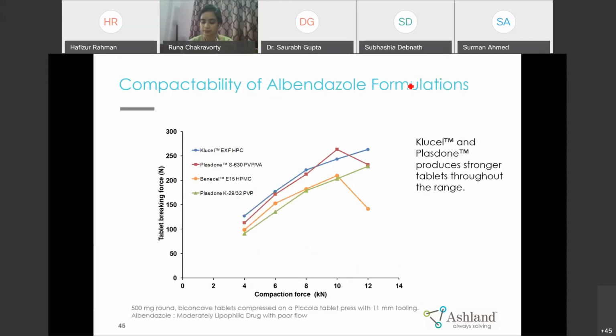Coming to albendazole, which is less hydrophilic or less soluble than metformin. Here you can see that we got the stronger tablet with Klucel, and next to Klucel with copovidone, but there is capping at 10 kilonewton. However, with Klucel, we did not find any capping in the tablet. Coming to povidone, we got tablet hardness lesser than tablets with Klucel or copovidone. So we can say that as API solubility is decreasing, as we go towards low solubility APIs, Klucel is working better than povidone.